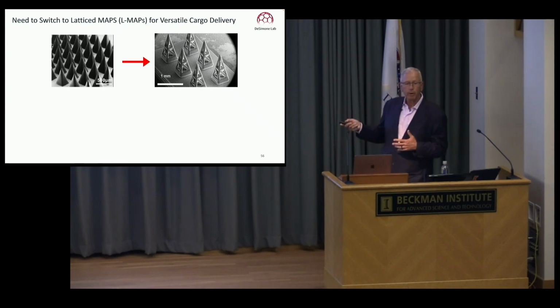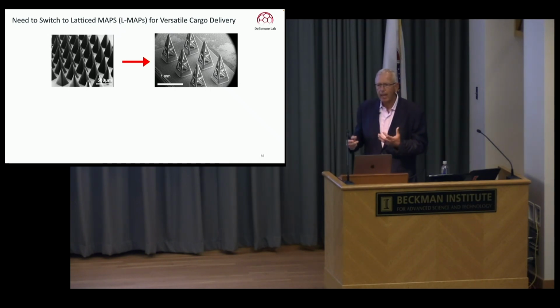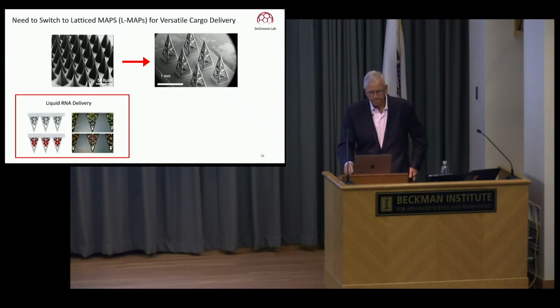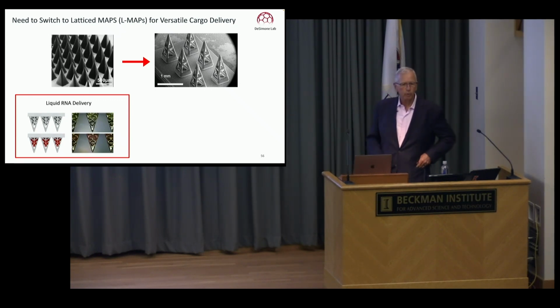With a high-resolution printer, we can now make amazing structures that can be a cage that can protect mechanically fragile materials or liquids. And so we could sequester droplets by controlling interfacial tension, and now we can inject liquids into the skin in an array of microneedles that are pain-free. These are less than a millimeter.